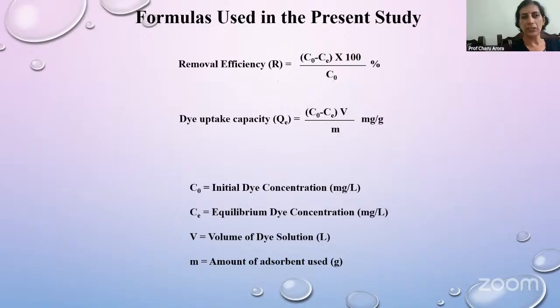Dye removal efficiency is calculated using this formula: C naught minus Ce. C naught is the dye concentration initially, minus Ce. Ce stands for concentration at equilibrium. When equilibrium is attained, the maximum removal is attained, into 100 by C naught. Dye uptake capacity, qe, in terms of milligram per gram, can be found using this formula.